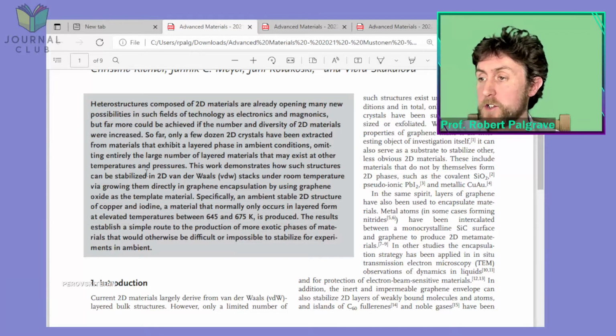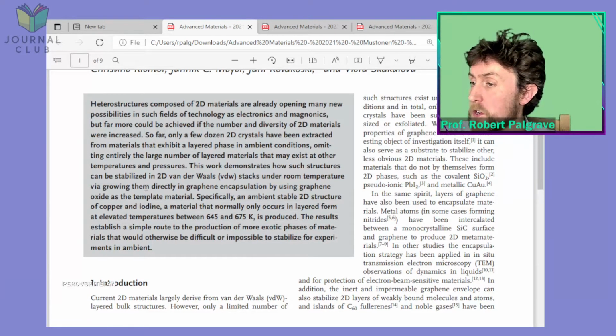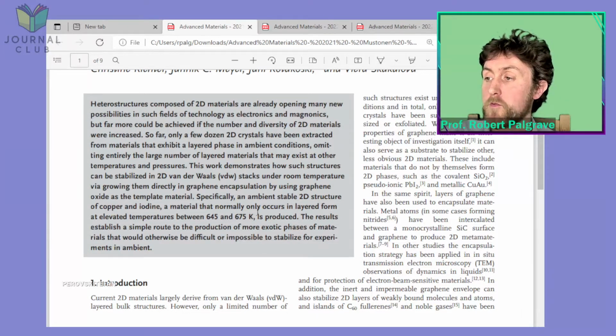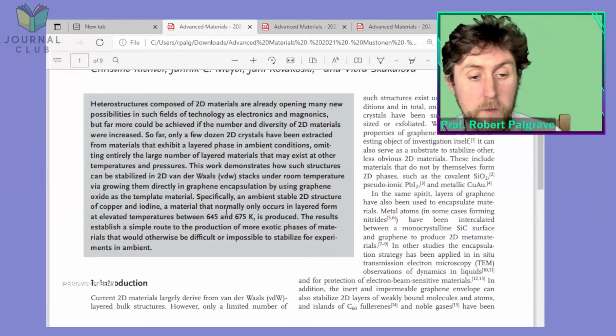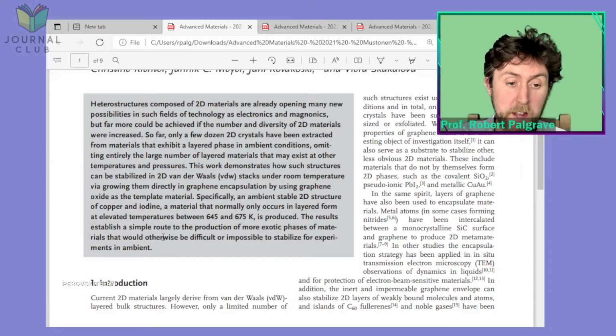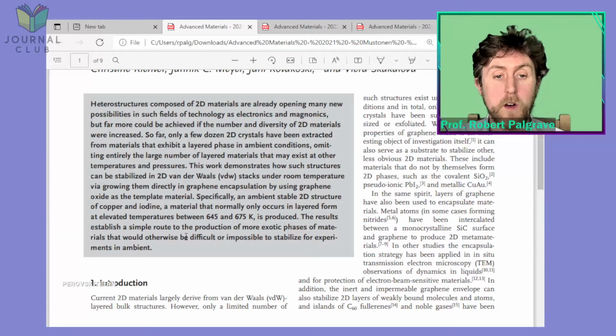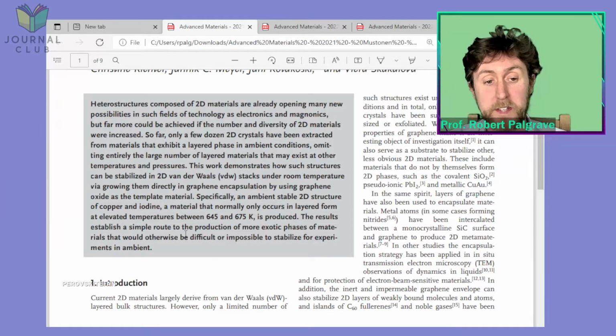This work demonstrates how such structures can be stabilized in 2D van der Waals stacks under room temperature via growing them directly in graphene encapsulation using graphene oxide as a template material. Specifically, an ambient, stable 2D structure of copper and iodine, a material that normally only occurs in layered form at elevated temperatures between 645 and 675 Kelvin, is produced. The results establish a simple route to production of more exotic phases of materials that would otherwise be difficult or impossible to stabilize for experiments in ambient. Okay, so as we hear there, the paper is about stabilizing 2D materials.